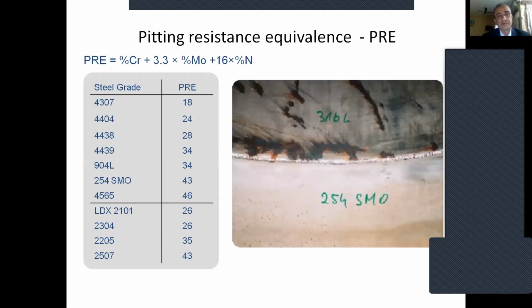This is the pitting resistance equivalent number. The pitting resistance equivalent number can be calculated for any kind of stainless steel like 304, 316, or maybe higher grade material. The higher the PRE, the higher the corrosion resistant property of that stainless steel. If I put 304 or 316 in a seawater application, it will corrode very easily. But if I put 2507 with a PRE number of 43, it can withstand for some time. It depends on the temperature as well as the chloride content. So the higher the pitting resistance equivalent number, the more corrosion resistant the stainless steel.